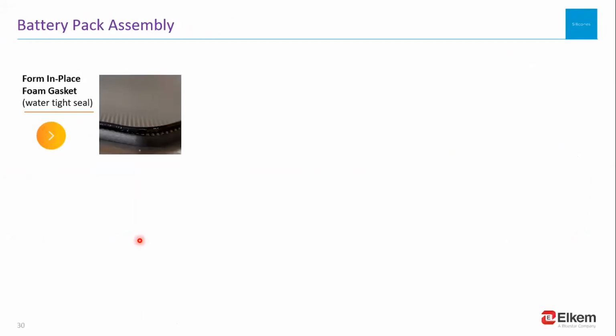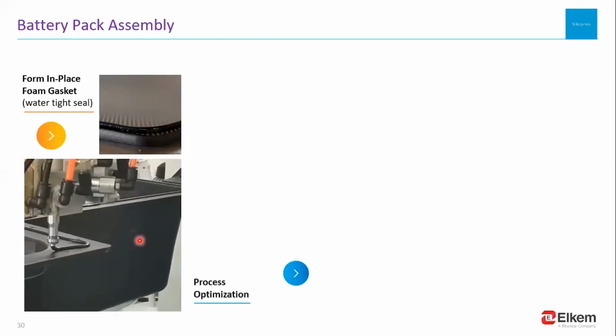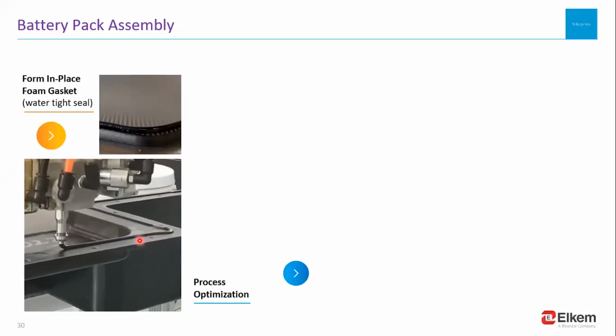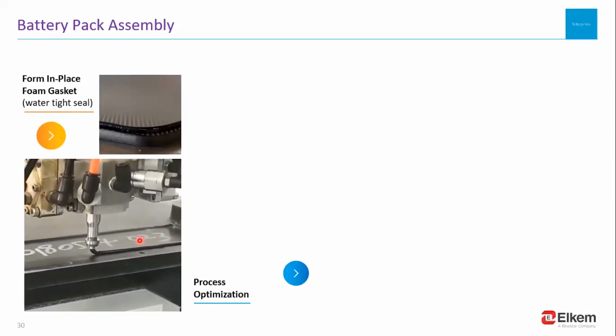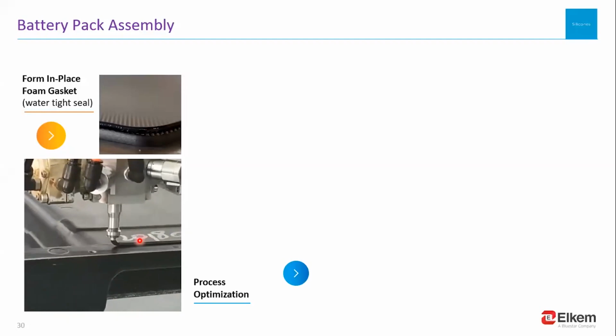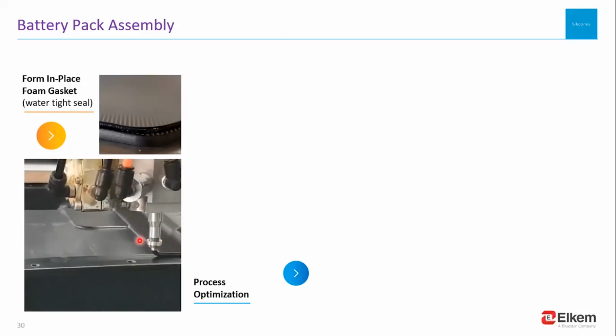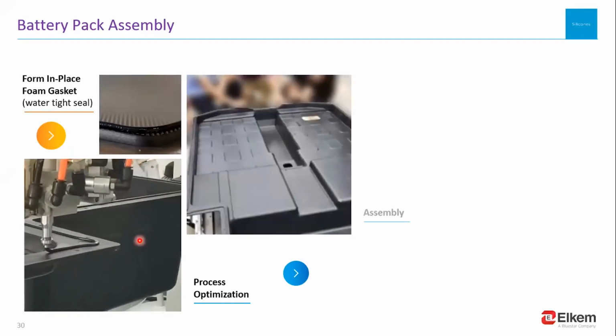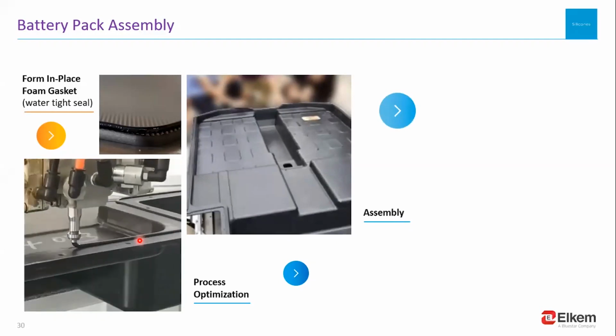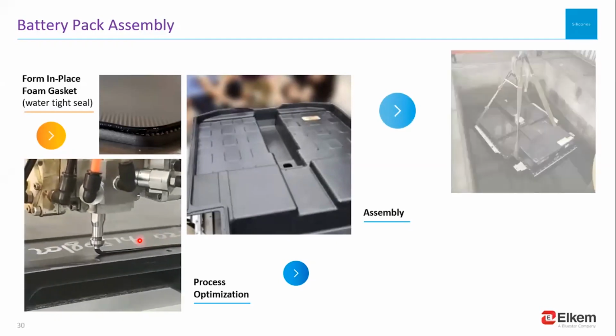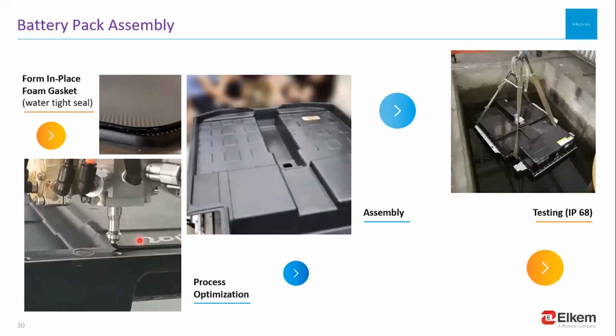In this case study, a silicone foam-in-place foam gasket was developed for the battery case assembly. It was learned that dynamic mixing of a thixotropic foam was necessary to get uniform bead shape and pore size. Through process optimization with the dispense platform, a high-quality seal was demonstrated by passing the IP68 water sealing test.